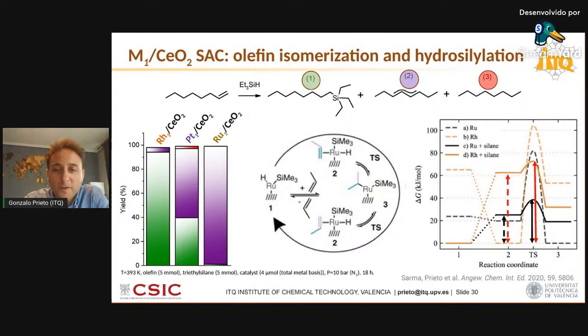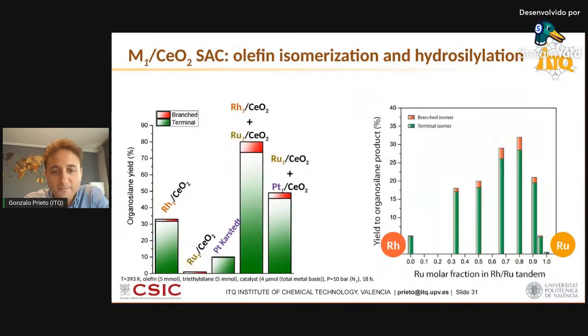So the olefin binds much stronger to ruthenium than to rhodium single centers, and that determines that on ruthenium, the preferred pathway is to isomerize the olefin into internal olefins, whereas on rhodium, the preferred pathway is to activate the silane, co-activate the silane and insert it to produce organosilane. So that reaction specificity offered by these two catalysts was something that triggered us to try the tandem integration of the two.